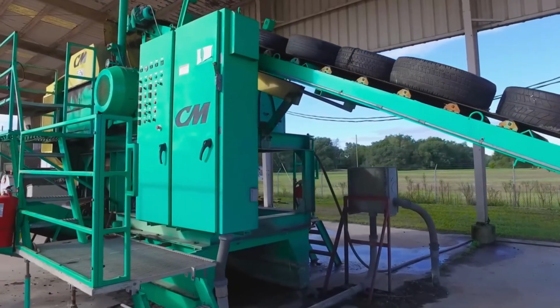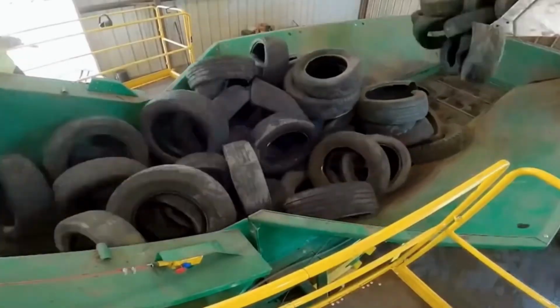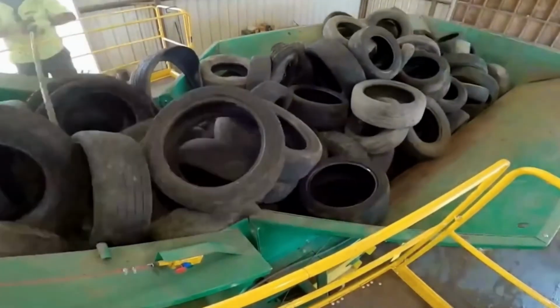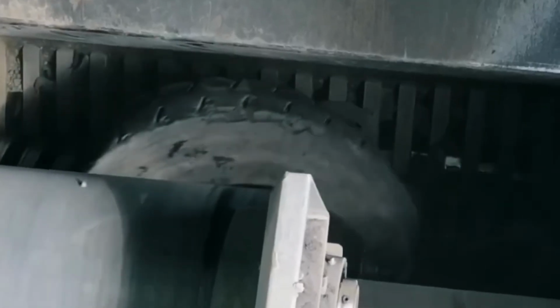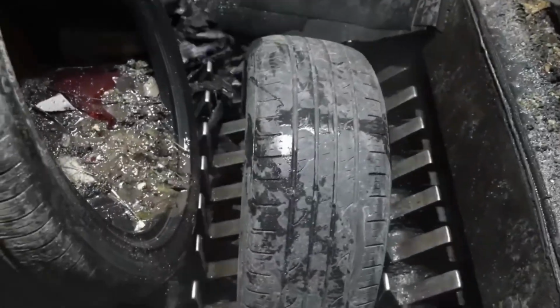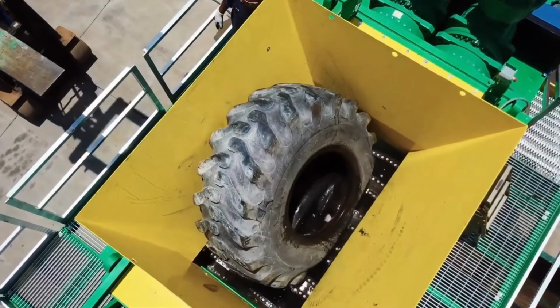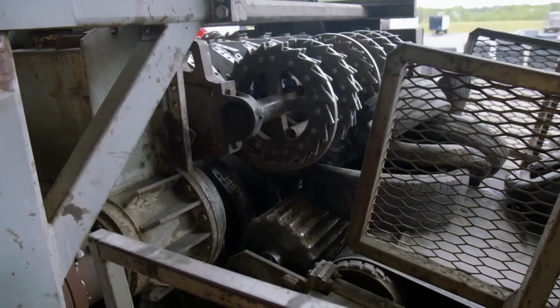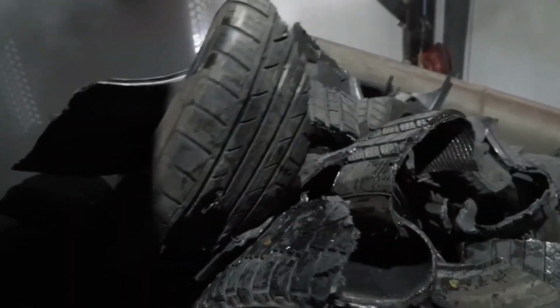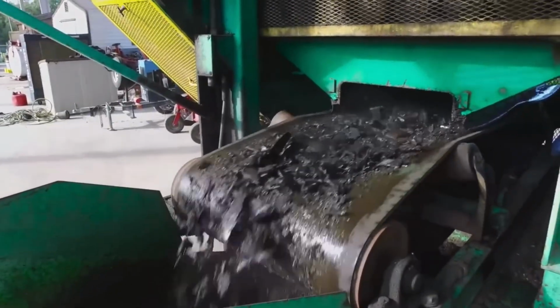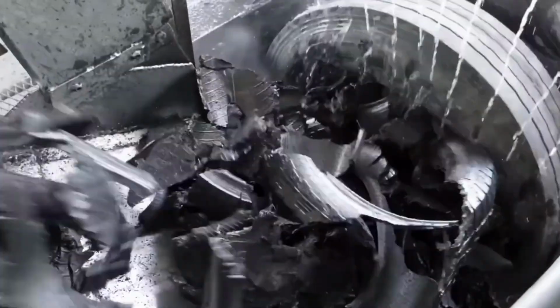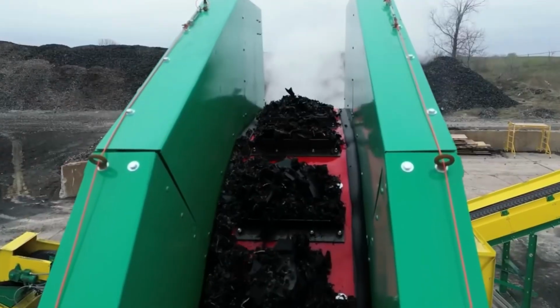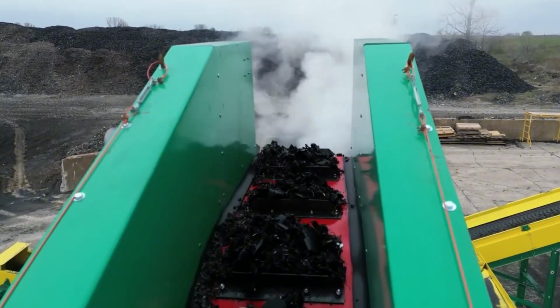In primary shredding, whole tires enter high-torque machines where slowly rotating alloy steel blades slice them into coarse fragments. Low-speed cutting minimizes heat, preventing rubber from softening or sticking while preparing material for further processing. Secondary grinding reduces fragment size further while mechanically fracturing remaining steel. Magnetic systems recover this metal directly from the flow, creating another recyclable stream. The final output is crumb rubber with controlled particle size. At this stage, the tire has lost recognizable form and becomes raw material for uses in construction, transportation, and manufacturing.